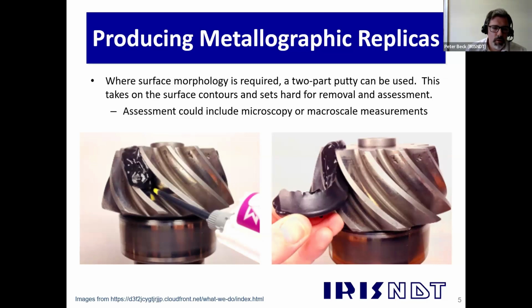And then as it goes onto the surface, it will take up the morphology of the surface and gradually cure. Now you can get different cure rates, anything from maybe 5 minutes to about an hour. You may think you want a quick cure time, but not necessarily, because once you've started the process, anything in that nozzle will start to try and cure. So if you've got a few components that you want to replicate, you would typically want something that cured over quite a long time, so that you had a long time to do your work. You'd get quite a few replicas out of one tube.